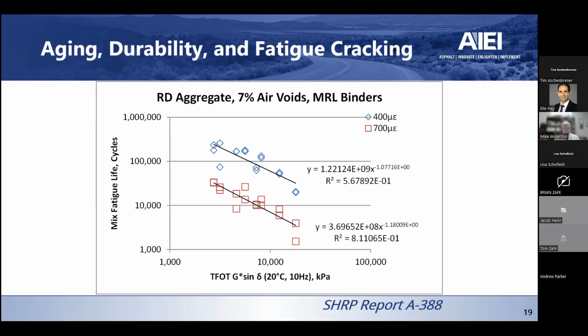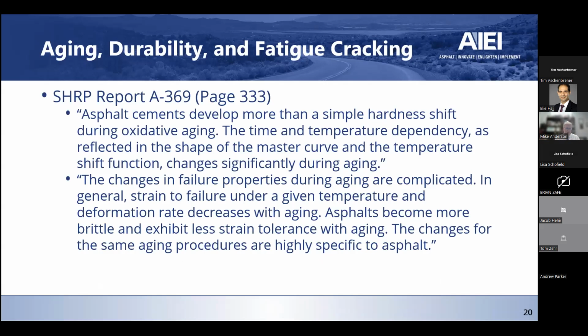But what you can see is that mixture fatigue life in the laboratory, generally speaking, responded to that G star times sine delta parameter. In other words, what we expect is that fatigue life is going to go down. You're going to have earlier cracking as the material gets harder. And that's what this is telling us more or less from these curves. They're not great. The R-squared values are 0.57, 0.81, depending on the strain level that you're looking at and what your responses are. There's a lot of variability that occurs in mixture testing, particularly fatigue tests, because it's a cracking test. So some of that variability we expect to see, but in general, they felt like, okay, this justified what we were seeing behind using G star times sine delta.